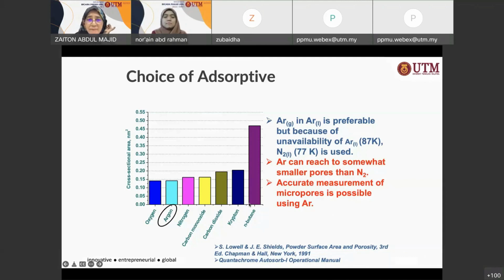Okay. So in this particular case, the choice of adsorbate: you have argon, nitrogen, carbon monoxide, carbon dioxide, krypton, methane. If argon is more preferable, and if we don't have argon, then use nitrogen. But we know that argon is very expensive. So that's why most of the time, most of them use nitrogen rather than argon. And argon can reach smaller pores. Argon and krypton are possible for micropores. So if you have micropores, it's better to use argon or krypton.